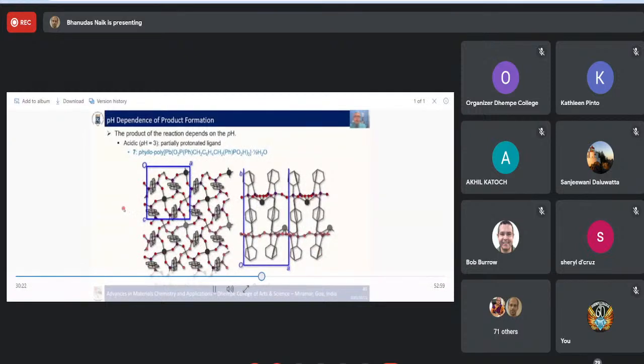In this compound, if you have a really acidic solution, you have a monoprotonated ligand, and you can see the phosphorus-oxygen-hydrogen bond here, which forms a hydrogen bonding interaction with a neighbor. You can see the neighboring oxygen on the side here, and this forms chains. It is a two-dimensional structure made up of these lead atoms, with bridges between two ligands. You have a three-dimensional structure, but the third dimension is hydrogen bonding.